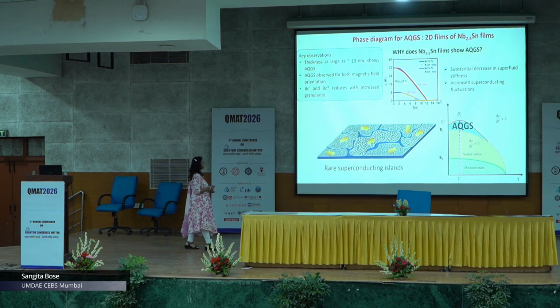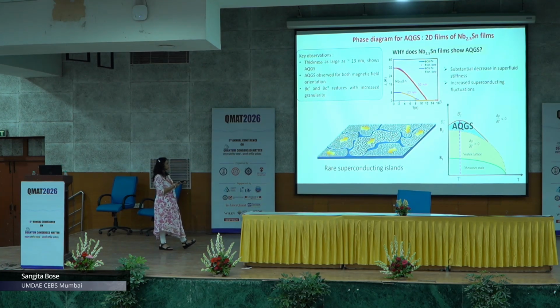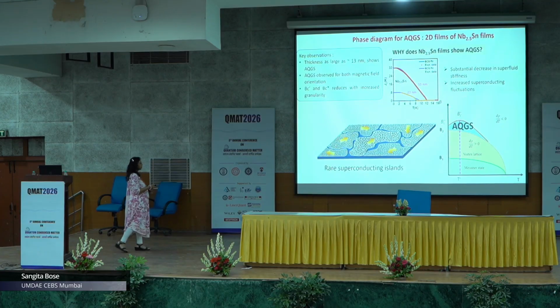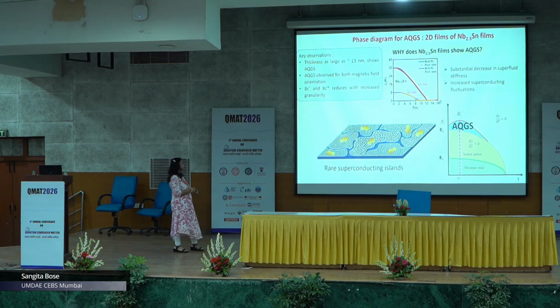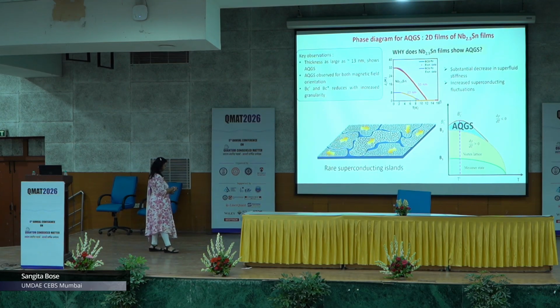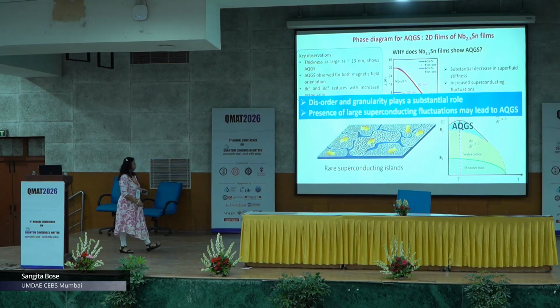We have already told you that in our system, of course, there is a large increase in the superconducting fluctuations, which is seen by the direct measurement of the superfluid stiffness. This gives us the idea that yes, superconducting fluctuations are quite high in our systems, and probably that is the reason why we are getting this kind of an anomalous quantum Griffiths phase in our system.